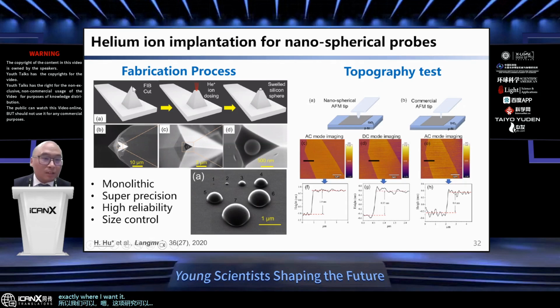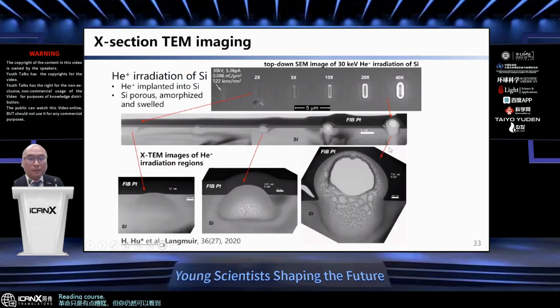Let's say this is a commercial AFM probe. I use FIB to cut a flat plateau at microscale, let's say 1 micron. Then I can focus the helium ion beam in the center precisely, and I can control the size just by controlling the implanting area. We can use this to do topography tests, compared with a commercial AFM tip. The resolution is just a little bit worse, but you can still see the graphene wrinkles pretty well.